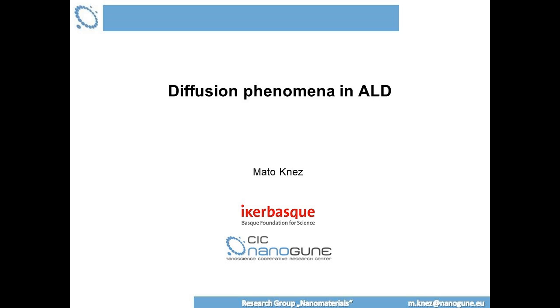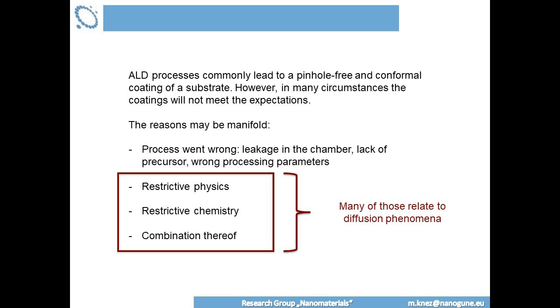An important point in ALD is to not only do depositions, but to deal with diffusion. And diffusion can have many, many different aspects. And when you do ALD processing, this is a slide which I showed some time ago at an ALD conference. You expect to have really a pinhole-free and conformal coating by ALD. This is what everybody claims being the main issue, the main point in ALD. But in many circumstances, you will not really meet your expectations. So you will have coatings which are not perfect.